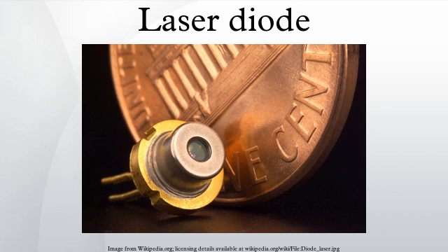The innovation that met the room temperature challenge was the double heterostructure laser. The trick was to quickly move the wafer in the LPE apparatus between different melts of aluminum gallium arsenide and a third melt of gallium arsenide. It had to be done rapidly since the gallium arsenide core region needed to be significantly under 1 micrometer in thickness.